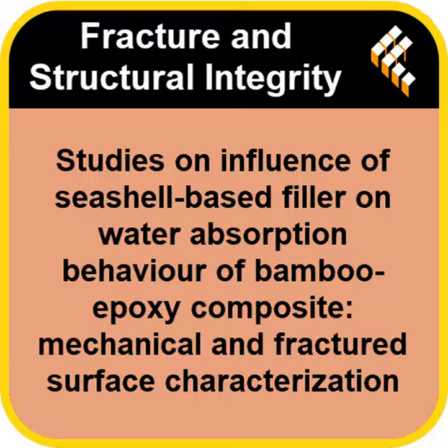Okay, moment of truth. Did the clamshells actually work as a barrier? What did the water uptake results show? They absolutely did. It was quite clear. The unfilled composite, the control, soaked up the most water, as expected, 5.85% of its weight. That's our benchmark failure point. And the ones with the filler?